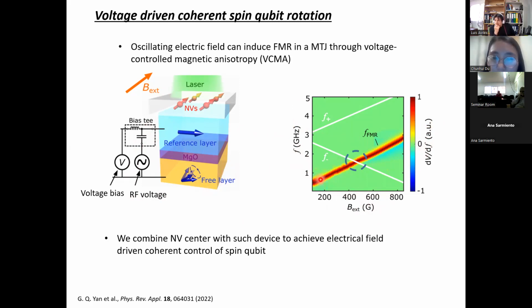And then, because we want to operate the hybrid devices, it requires that the microwave field generated from the FMR precession match the NV electron spin resonance frequency, so it can drive the coherent rotation of the qubits. So in this case, we want to find a sweet spot where the FMR frequency matches the NV frequency. Based on the STFMR results, we find the FMR frequency crosses the NV frequency at 400 Gauss. So this will be the field we can use, the field from the hybrid device, to drive the NV center.